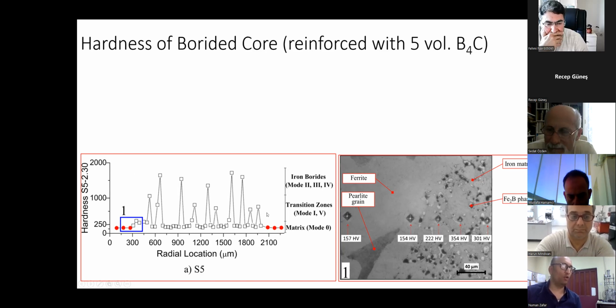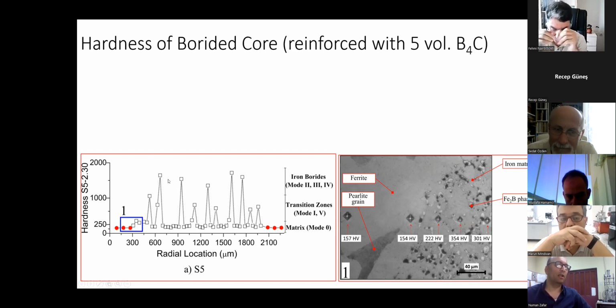It belongs to the Fe2B phases. But it is very overwhelming to see that you have a material which has a variation of such contradicting properties. You have a wire which has a sheath which is so ductile that you can bend it, but at the same time in the wire core, you have iron matrix and iron boride phases which can reach a hardness of about 1950 Vickers hardness.